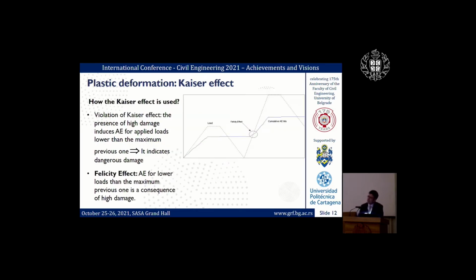Another use of the Kaiser effect is when it is violated, when it is not being confirmed. That is when acoustic emission is emitted with an applied load that is below the previous maximum one. What does it mean? Well, as the Kaiser effect is considered universal, if it is violated, it means that serious damage is present in the structure. If you have a global emission from all the structure, it means that a lot of damage is there, and you have to be very careful of what is going to happen with it. It is called the Felicity effect, that is, acoustic emission at lower loads than the maximum previous one is a consequence of the presence of high damage.